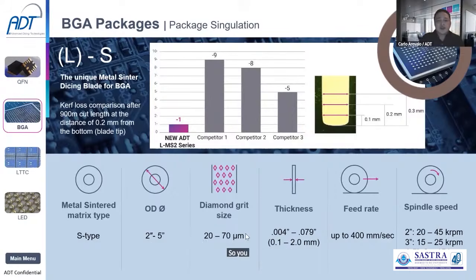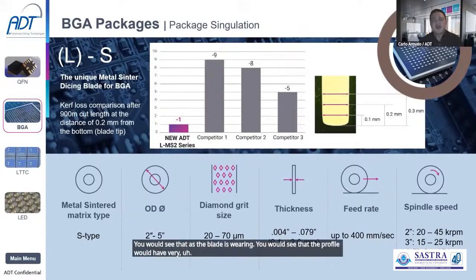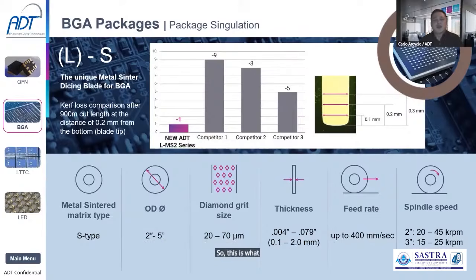So you would see on the right side of this drawing that as the blade is wearing, the profile would have very insignificant change. This is what you want to maintain in order for your package size to be within the specs or within tolerance, because the main failure for BGA blade applications is the package size going out of spec.